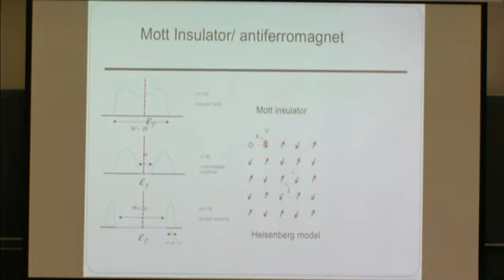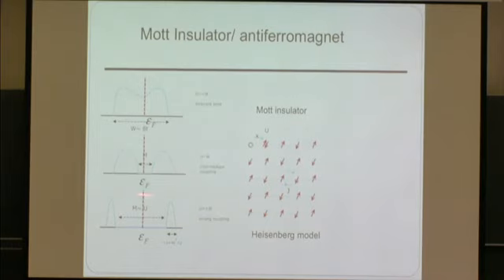Now take U even larger, and in this limit, you can actually use a local picture in real space where two electrons cannot occupy the same site because of the U energy. So at half filling, namely each site with one electron, you reduce to localized spins, described by the Heisenberg model. You see the lower Hubbard band is filled up, such that each site has one electron, but the spin is not frozen yet, so it could point up or down, and so there's only the spin degree of freedom left.